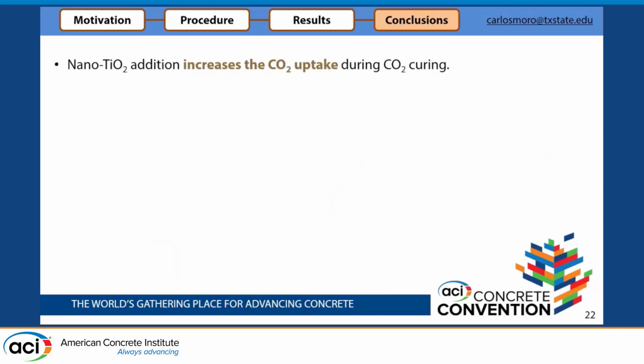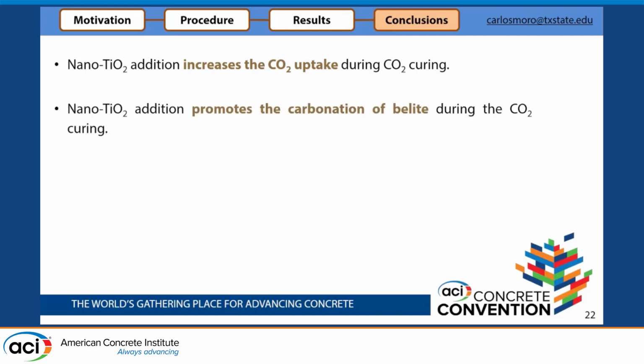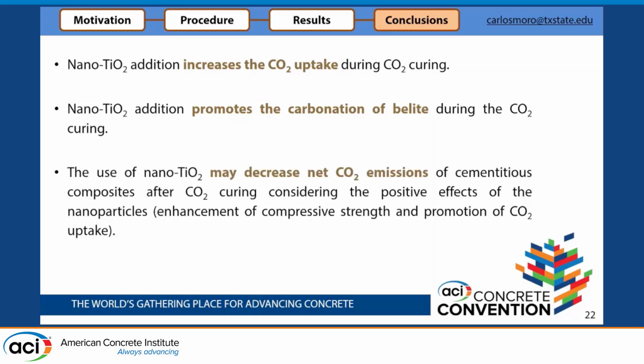So our conclusions for this study were that the nanotitanium addition increases the CO2 uptake during the CO2 curing, that this addition also promotes the carbonation of belite, especially in samples with CO2 cure, and that the use of nanotitanium dioxide may decrease the net CO2 emissions, but we need to consider that in the unit that we are using. So the functional unit that we decide to use should be one that basically contains not only the volume but also properties of the sample, like compressive strength and promotion of CO2 uptake. And we know that these nanoparticles also have positive effects during the durability, so this can be further improved if we consider durability as well.